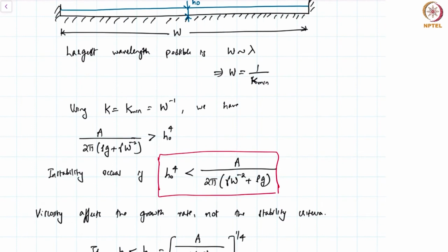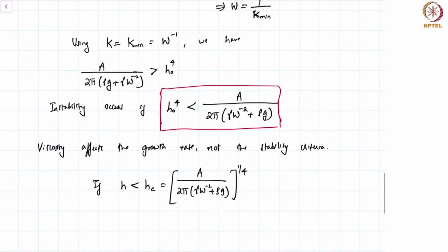Now, if the thin film is larger than a certain value, meaning greater than this critical thickness, Hc, then you would expect that the van der Waals forces are not very dominant. But there are many other physical processes at work in a real laboratory experiment. For example, the thin film could constantly keep evaporating, and there will be a point where the thin film thickness becomes comparable to this Hc. And then once this happens, van der Waals forces will eventually drive the thin film to rupture.